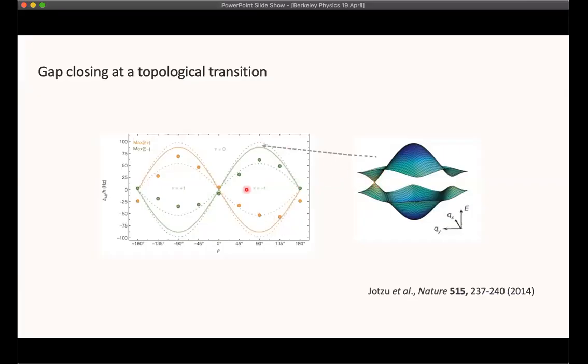And so this group was able to probe that topological phase boundary by measuring the relative populations in the lower and upper band, or actually by measuring the transfer of populations. This transfer should only happen if the gap is closed. And so that's exactly what they show here, that there's a maximum transfer occurring exactly at the point in phase space where the gap closes.